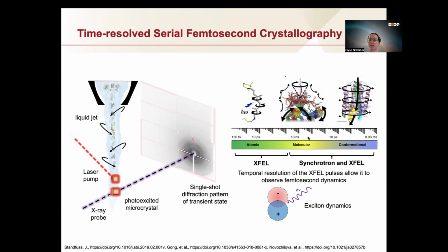So you can measure those things at a synchrotron. But if you're looking at atomic motion, like a photoactive molecule that has some kind of bond oscillation, you really are kind of stuck at the picosecond and femtosecond time range. And in material science, what we can do is potentially study things like exciton dynamics and other ultra-fast dynamics in materials by looking at structural changes.